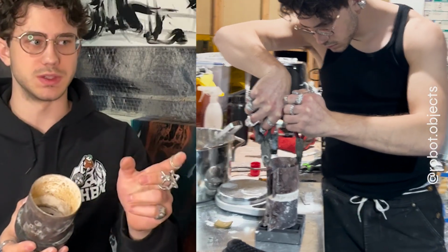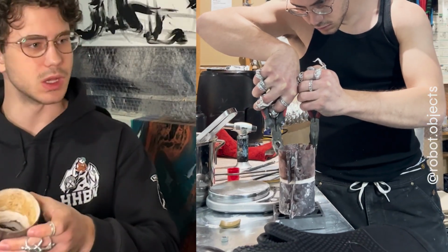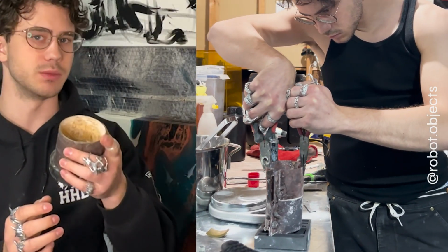We initially started with these collars that I made. The issue with the collars is it was thin metal, so the more you heat it up, because we go almost to 1,000 degrees for 2 hours, it just started weakening that metal over time. So we had to step it up to something thicker. On top of that, the collar was nice because you can put it all the way around and then tighten it down, and you can take it on and off. It kind of saved us in this cast, the one that you see, our fail.